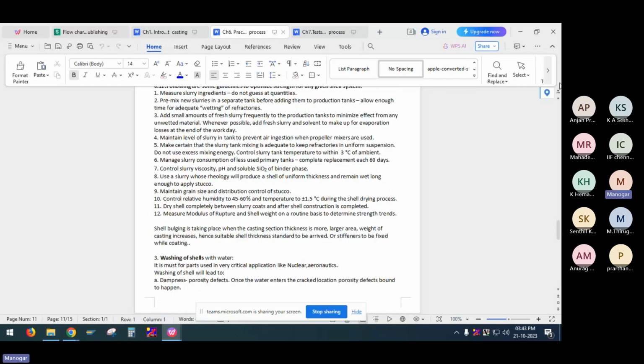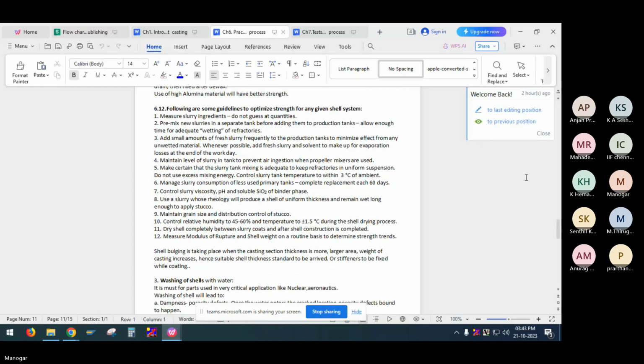And some of the points to optimize the shell strength. Measure slurry ingredients, do not guess, and quantities. Pre-mix new slurries in a separate tank before adding them to production tanks. Allow enough time for adequate wetting of refractories. Add a small amount of fresh slurry frequently to the production tank to minimize the effect from any unwetted material. Whenever possible, add fresh slurry and solvent to make up for evaporation losses at the end of the workday.